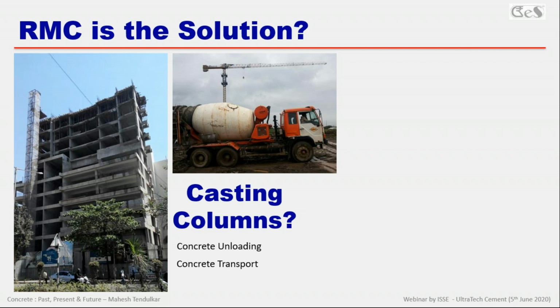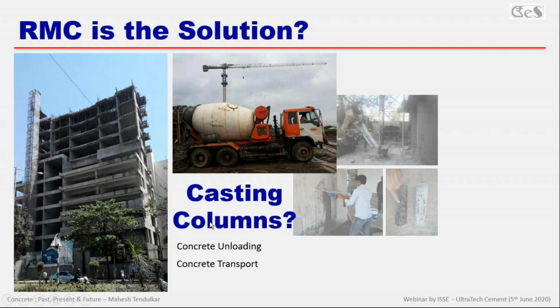And this is a real case study of one of the buildings in Mumbai. There was a transfer girder cast at this location, maybe on the 7th floor, and the consultant feared that there was something wrong, so he wanted to take a core of that column. After taking the core, it was a surprise: the concrete had not achieved even about 60% of its strength even after 3 months. So what went wrong? We analyzed it, and this is what we found.